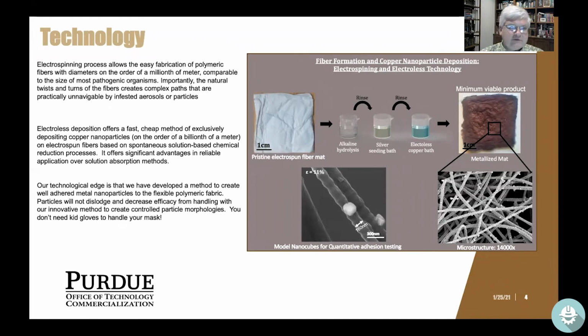And so what we did in our particular approach to the technology here has been to say, we take an existing technology like electrospinning, nothing particularly new, been done for decades, and it can make a non-woven fabric. The fabric is flexible, it can be used in a mask, or it can be used as an insert in place of a mask. And what we do is we put copper nanoparticles onto that non-woven polymer fiber. So we have fibers that are somewhere between 100 nanometers and a micron in diameter, and we coat them with copper nanoparticles. The key here is that electroless deposition, also not a particularly new technology, it's been around for over 100 years. If we use the right conditions and we create the right morphology, we can get well-adhered copper nanoparticles onto this electrospun fiber mat or fiber mask.